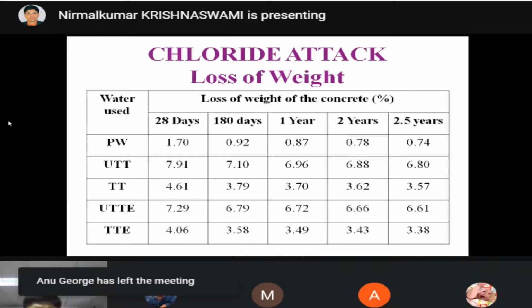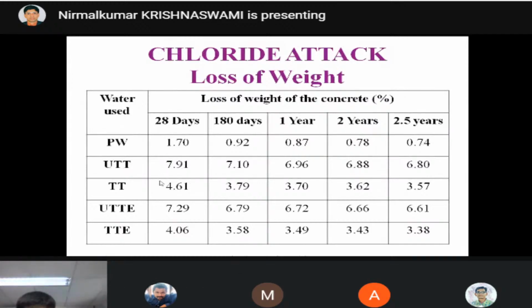So for potable water, at the end of 28 days, it is 1.70. At the end of 2.5 years, it is 0.74. Similarly, you see the second thing, it is very dangerous, alarming, 7.91 and 6.8. This is for tannery effluent. This is for textile effluent.